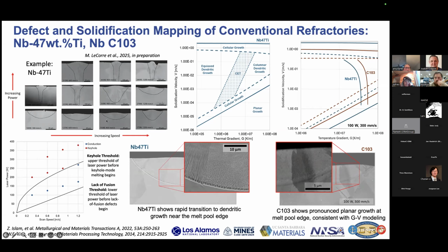And my student Megan has been doing quite a bit of work trying to optimize the processing conditions that we use and control defects during processing. And then she's really been doing a lot of this solidification mapping and CET mapping. So shown here are just some examples for the niobium Ti as compared to the C103 and the different types of solidification morphologies we get.